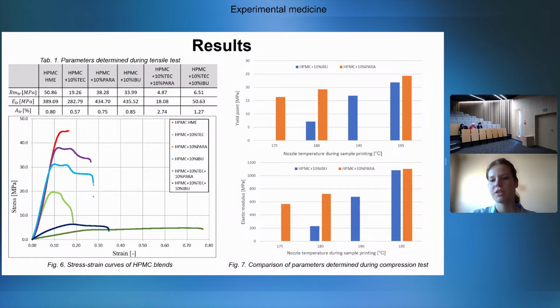Compression tests were additionally used to measure yield point and elasticity modulus of HPMC and active ingredient blends at different temperatures of the nozzle during printing of the samples. Blends containing paracetamol had higher compressive strength, and it can be noted that as the temperature of the nozzle increased, so did the value of the parameters, as can be seen on the graph in figure 7 on the right.